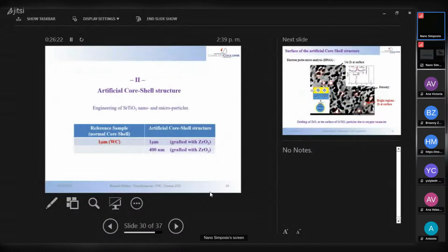Now, we did that, and then we did another thing: we grow artificial core shell structures. The aim of this is to make engineering of strontium titanate nano and microparticles. So we have a reference sample, which is particles of 1 micron size.